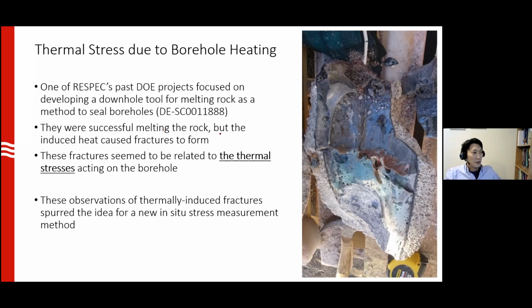They were successful in melting the rock, but they also realized that the heating caused many fractures around the borehole, which you can kind of see by the rough edges here. I think the center portion is the molten rock, whereas the surrounding is the brittle fracture that formed around the borehole. They noticed that heating induces a significant amount of thermal stress. And this led to the idea that maybe you can use this. For that project it had a detrimental effect, because they were trying to seal the borehole but were introducing fractures around it. So now they thought about using this to intentionally create breakouts.